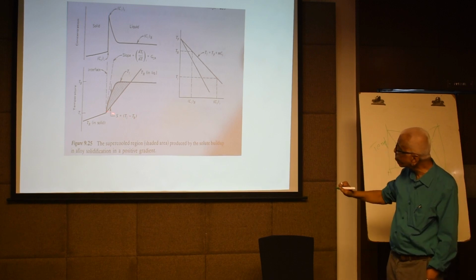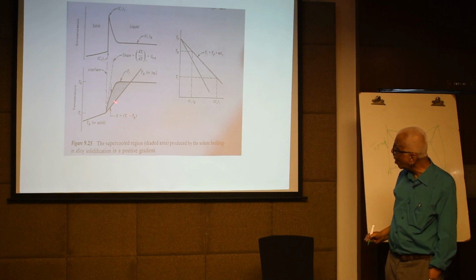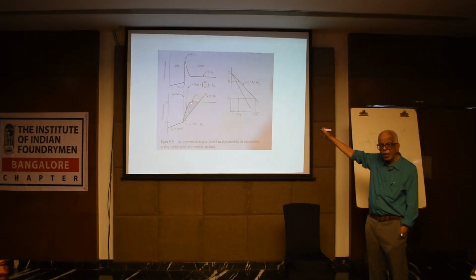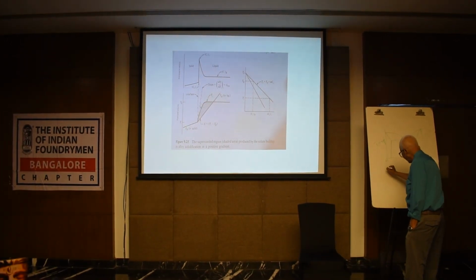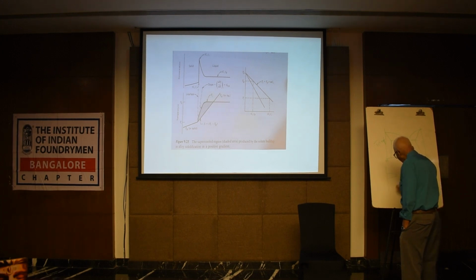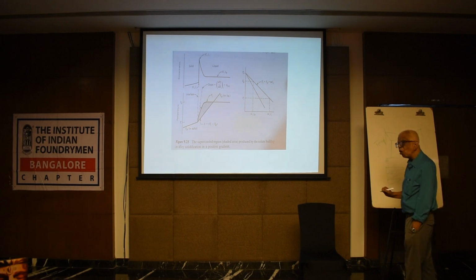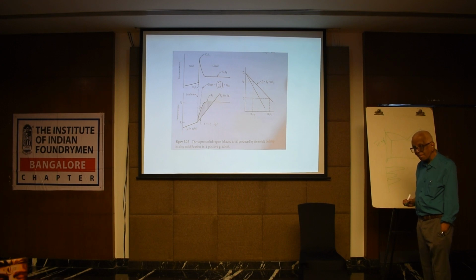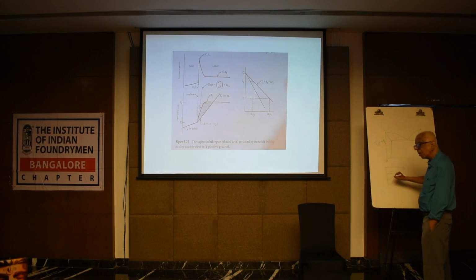If a bump forms, for example, a bump on the solid-liquid interface, the bump will see more undercooling. The interface breaks down into a cellular interface, and that's due to solute rejection at the interface. Solute gets rejected, then there's a buildup of solute and a concentration gradient. There's a small diffusion layer ahead of the interface. That's the reason why constitutional supercooling occurs, and the interface breaks down into a cellular or a dendritic interface.